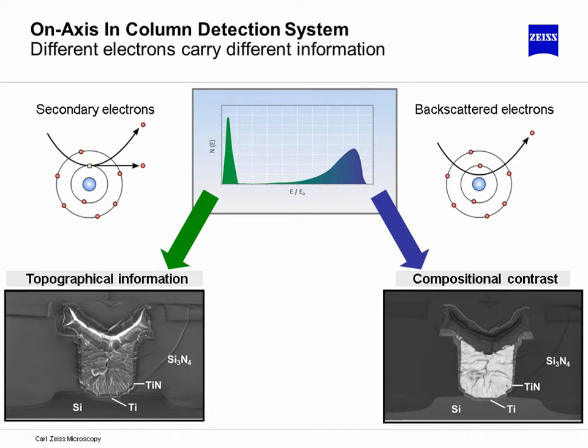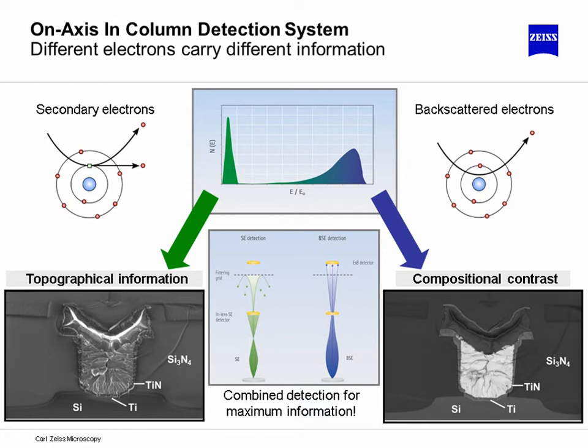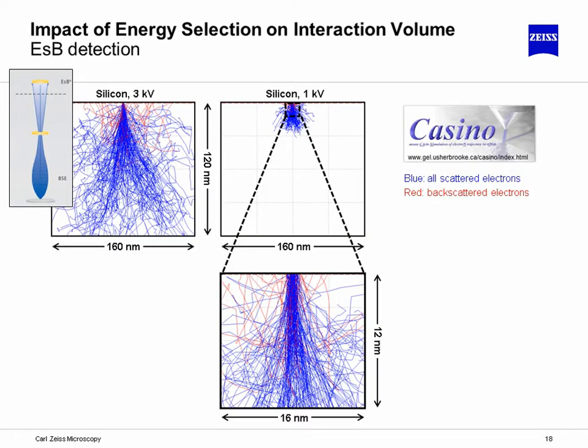Here you can see a plot. The central top graph is a plot of the energy or the distribution of electrons as a function of energy. These are the electrons that emerge from the sample once the sample has been impacted by the primary beam. The different electrons, for example, in green, the so-called secondary electrons, carry different information, in this case topographical information, while the electrons in blue, the backscattered electrons, have interacted with the nuclei of the elements present in the sample, and they carry compositional information. At 1 kilovolt, as you can see, the information depth is still greater than 10 nanometers.